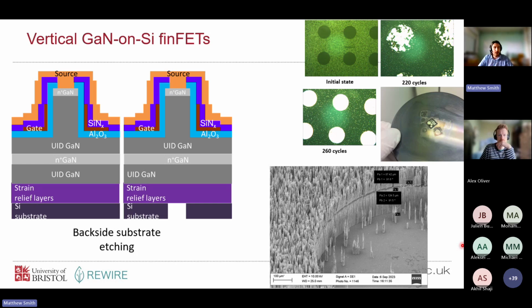And the second generation, we were still essentially following the work from Thomas Palacios's group in MIT. So in terms of design, that wasn't too tricky, but optimizing the processes, I showed earlier some slides on the resist etch back process, that kind of thing. That is quite challenging. Certainly as we move to higher density multi-fin devices, that's going to be more challenging again. But it's all just essentially an engineering challenge. The third generation was less of an issue, I would say, because it was relatively small changes to the design, just flipping that layer. That was more inspiration from Chengji's side to realize that actually, it's important to protect the fin during that process. So yeah, it varies depending on where we are in the production cycle, I suppose.